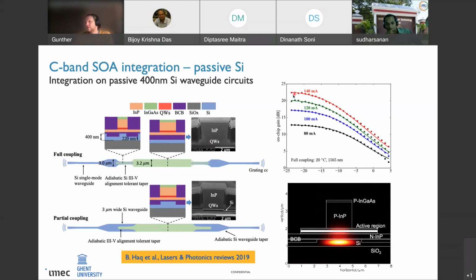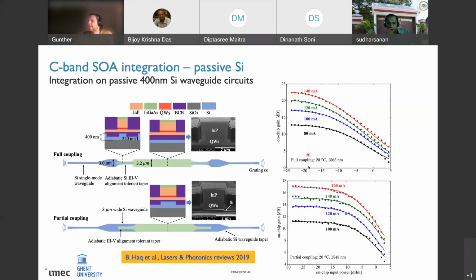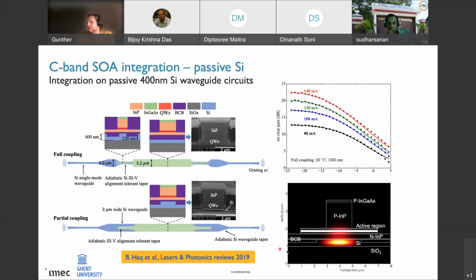Clearly, this top structure here will have a larger gain because the overlap between the mode and the quantum wells is higher in this case. However, the case of the partial transfer is also interesting because then you get a higher output saturation power. Moreover, the fact that you have this silicon below implies that your coupling structure here becomes more alignment tolerant. So for most of our current research, we are focusing on this kind of III-V on silicon active cross-section, where the light is partially in the III-V and partially in the silicon.